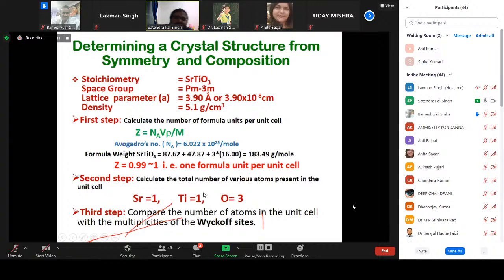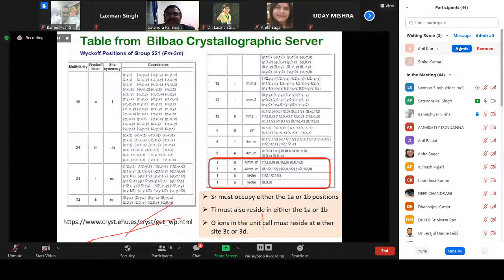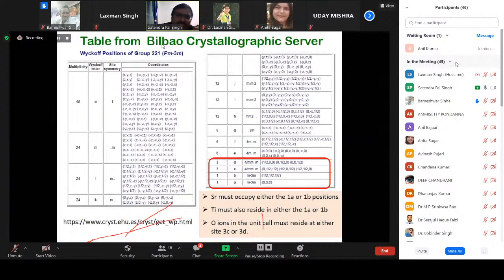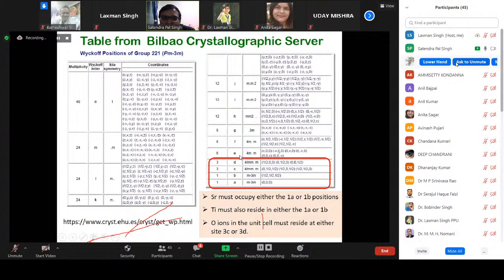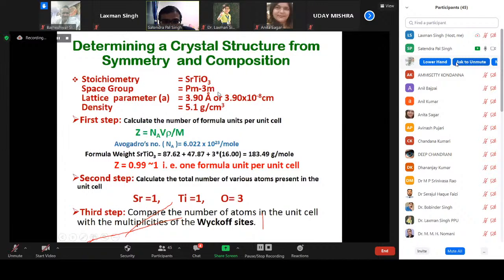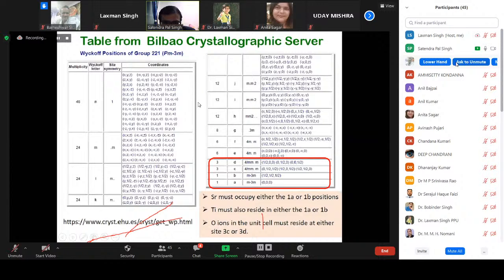Now, the next step: where they lie in the structure. So we have to find the Wyckoff sites. Wyckoff sites can be obtained from the Bilbao Crystallographic Server. If you know the space group, you can find this crystallography table, or you can also use the International Table of Crystallography Volume A. For example, this is the Wyckoff table for Pm3̄m.